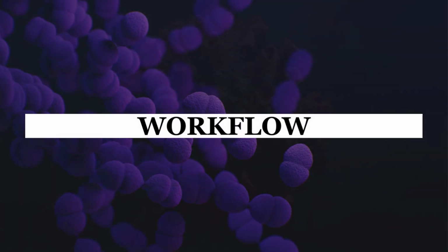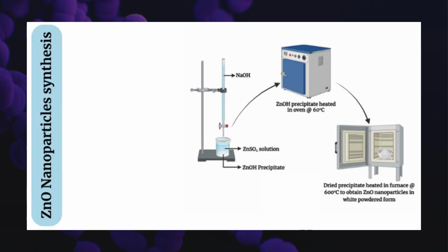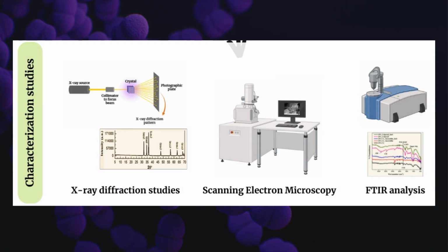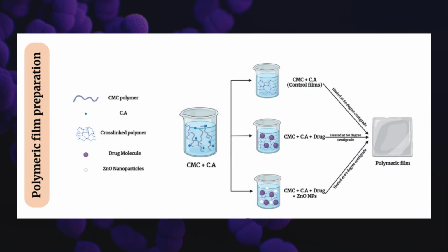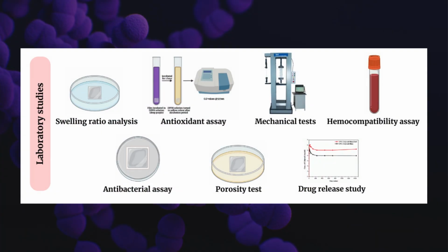Workflow. This study aims at synthesizing ZnO nanoparticles, analyzing the structure and morphology of the nanoparticles using SEM, optimizing the formulation of CMC-based polymeric films loaded with ZnO nanoparticles and antibiotics, and analyzing the film's swelling properties, antioxidant properties, hemocompatibility, mechanical strength, antibacterial efficacy, and drug release pattern.